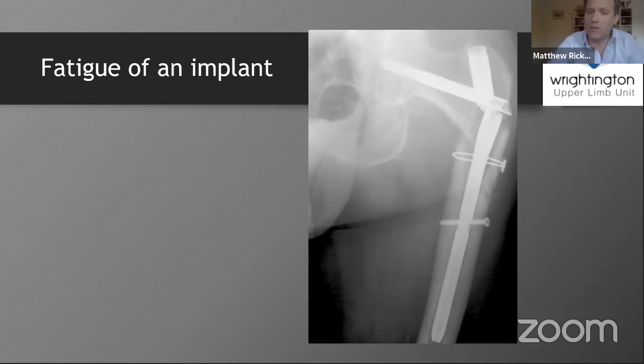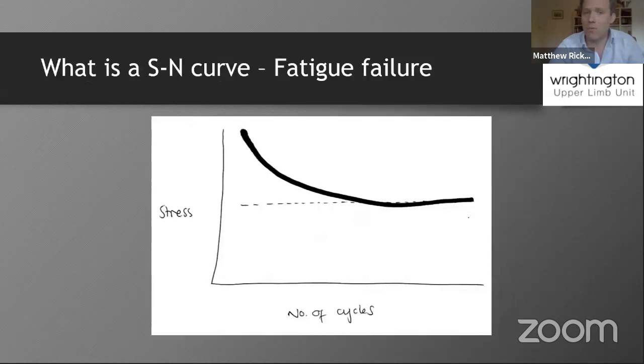I don't know whether the screw may have notched or weakened the nail as it went through, but there is definitely a weak point at the hole where the screw goes through the nail, so this fatigued at that point because of cyclical loading through it. Whether this is because the fracture didn't heal, or the weight was too much, or there were too many cycles, all of this occurred before it was able to heal. So this failed by fatigue at a common point.